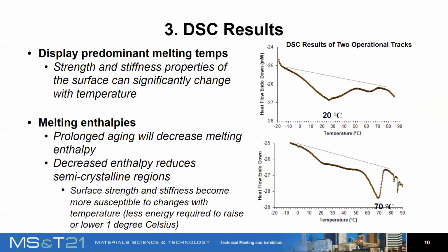Now, you can see here two operational tracks are visible. The top graph shows a melting point at around 20 C, where the bottom graph shows the predominant melting point to be about 70 degrees Celsius. As the surface warms, we can see the mechanical properties become more susceptible as these melting points differ. And these different melting points can also tell us the enthalpy and crystallinity of these samples as well.